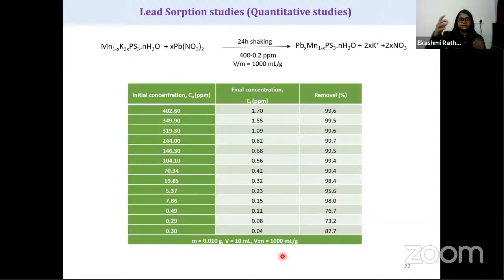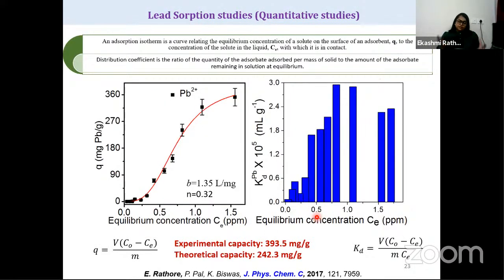Here you can see that the initial concentrations range from 400 to 0.3, and my final solutions have decreased. See, such a low concentration I have got for the lead. So we found out that there is more than 99% removal of the lead happening in our system. Now we wanted to calculate what the capacity of this material will be, and how much lead it can capture. So we took different concentration solutions, and used our material to capture.